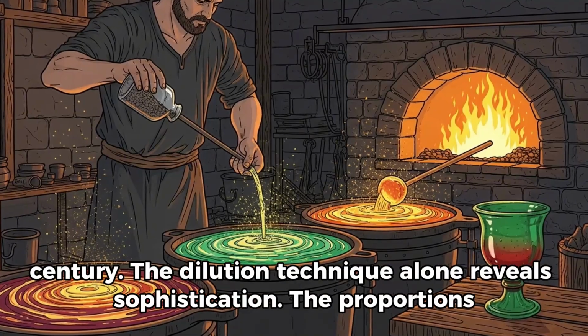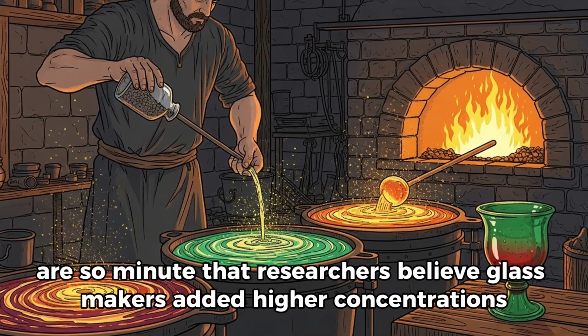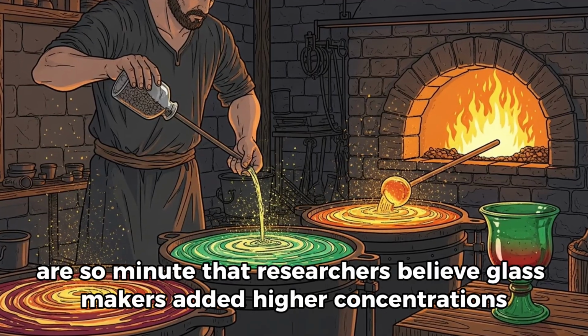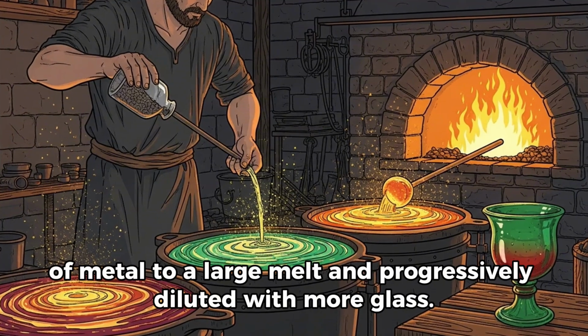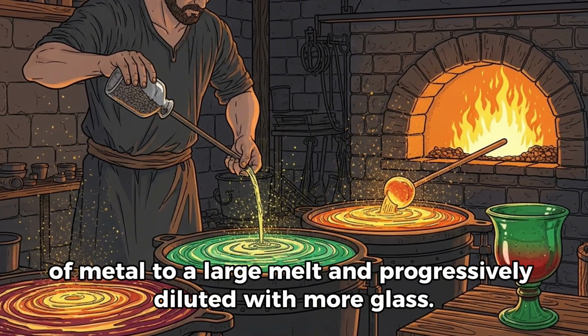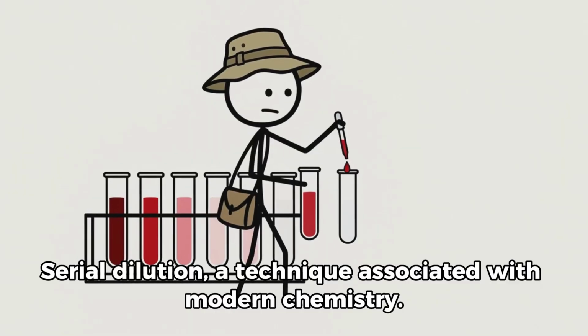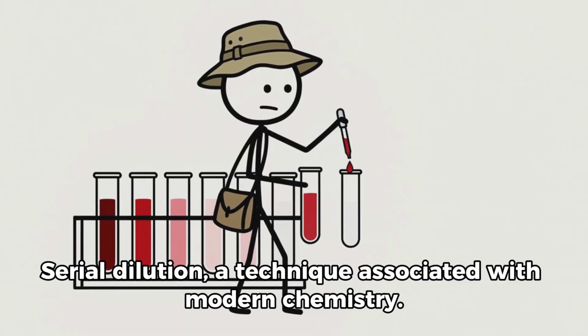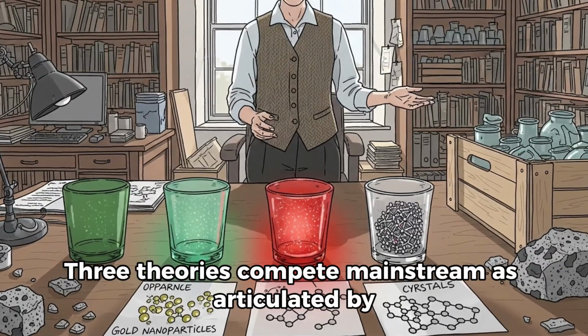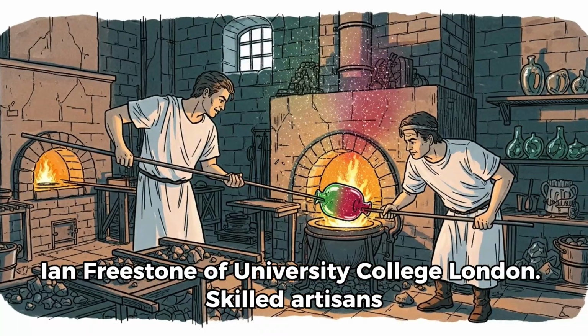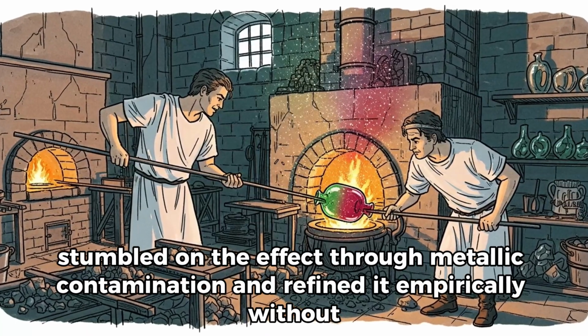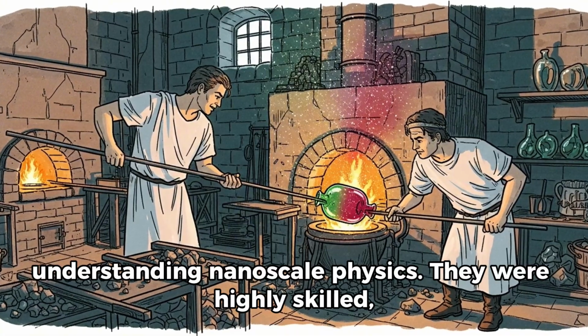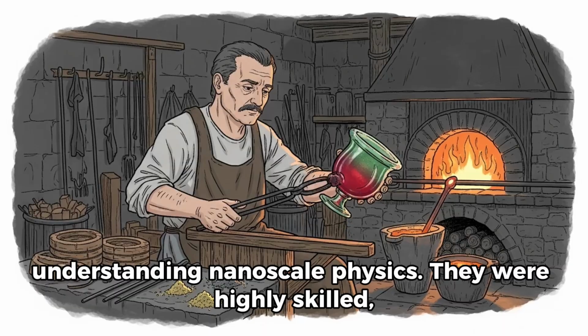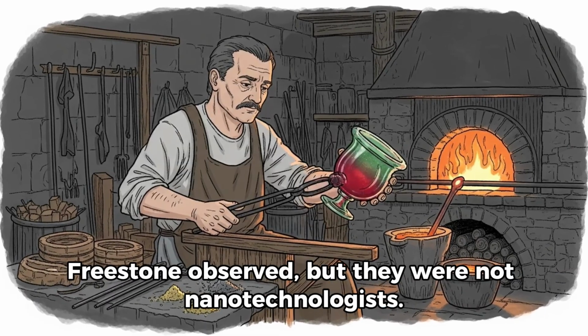The dilution technique alone reveals sophistication. The proportions are so minute that researchers believe glassmakers added higher concentrations of metal to a large melt and progressively diluted with more glass. Serial dilution, a technique associated with modern chemistry. Three theories compete. Mainstream, as articulated by Ian Freestone of University College London: skilled artisans stumbled on the effect through metallic contamination and refined it empirically without understanding nanoscale physics. They were highly skilled, Freestone observed, but they were not nanotechnologists.